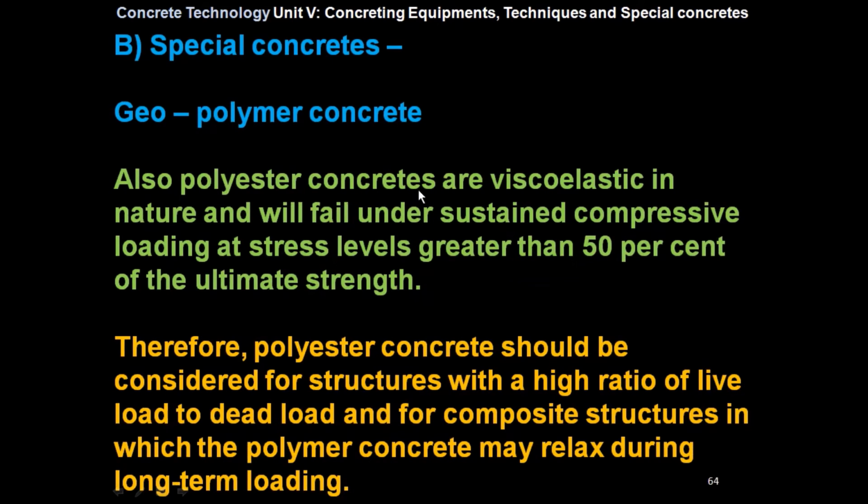Also, polyester concretes are viscoelastic in nature and will fail under sustained compressive loading at stress levels greater than 50% of the ultimate strength. Therefore, polyester concrete should be considered for structures with a high ratio of live load to dead load and for composite structures in which the polymer concrete may relax during long-term loading.